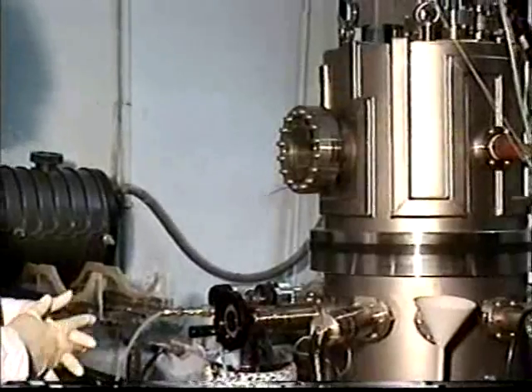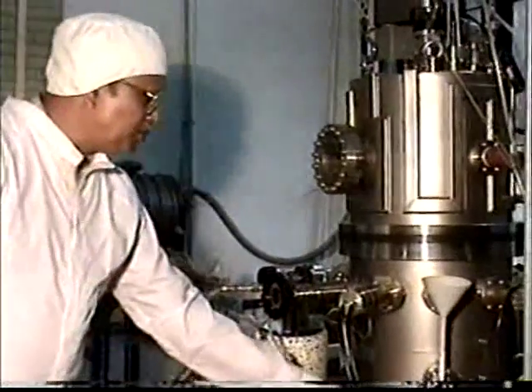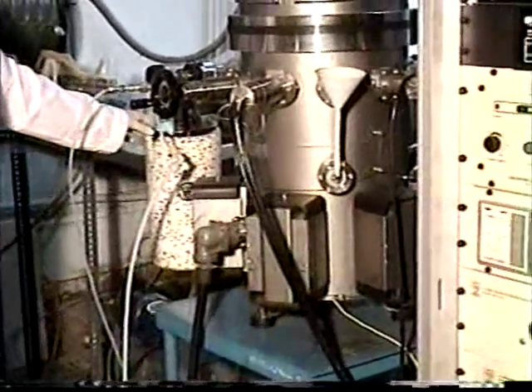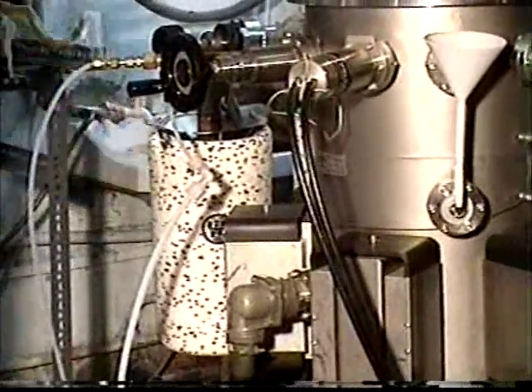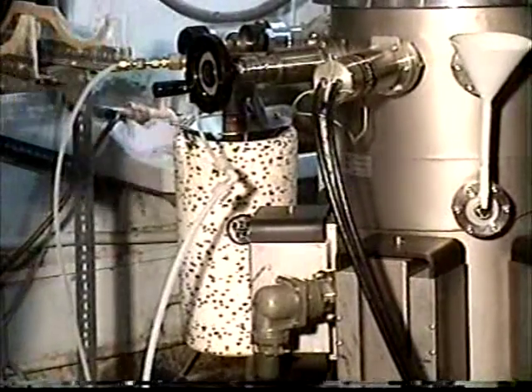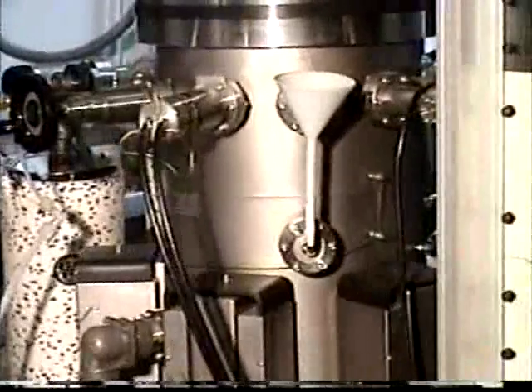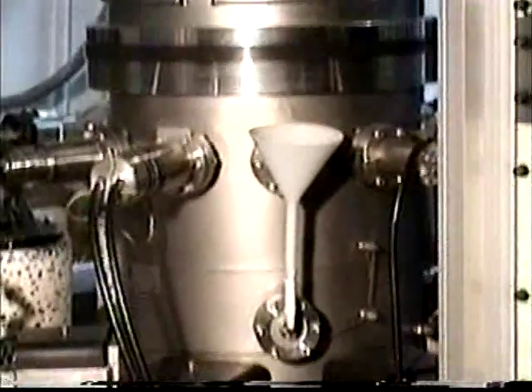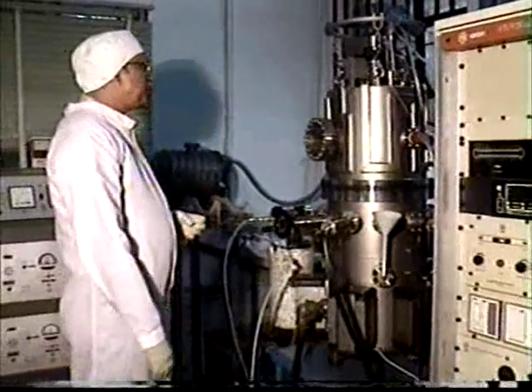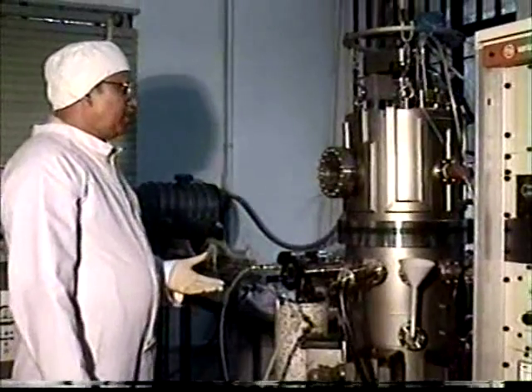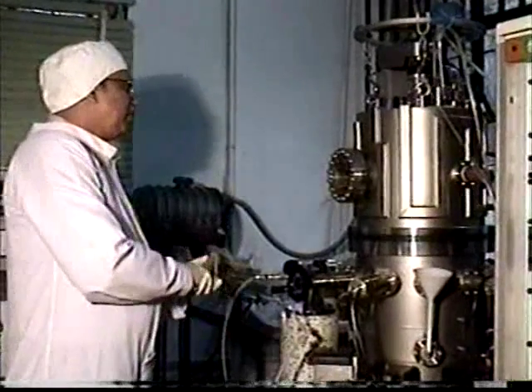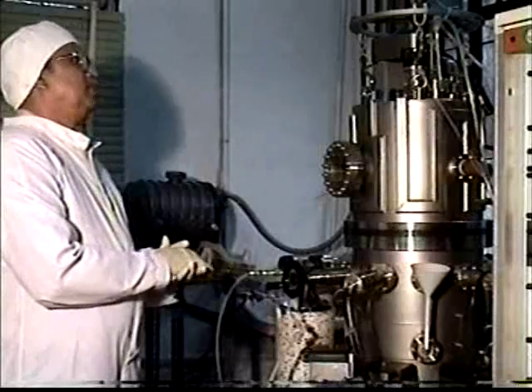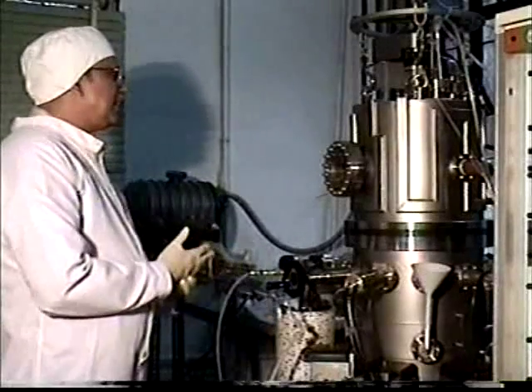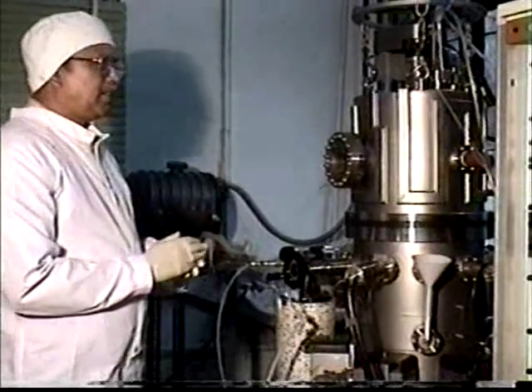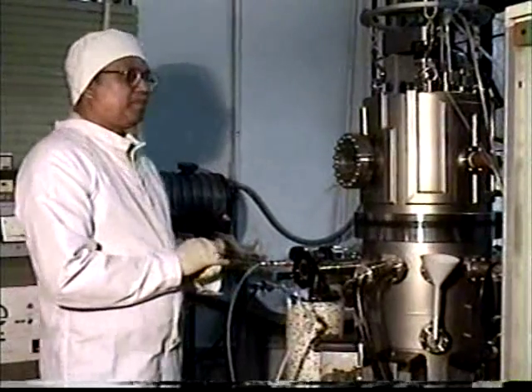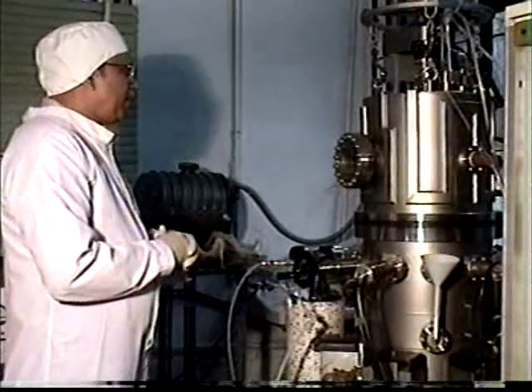The pumps used in this machine are an ion pump, which you can see here, a cryosorption pump, which uses some liquid nitrogen, and a titanium sublimation pump, which is here. So with the help of these three pumps, we can create vacuum inside the chamber of the order of 10 to the power minus 10 millimeter of mercury. And when the deposition is being done, the pressure will increase to nearly 10 to the power minus 7 millimeter of mercury. So it is very low.